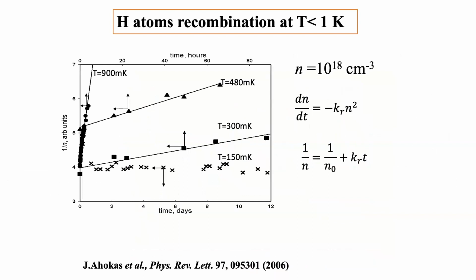We performed this experiment for the first time in 2006, measuring the rate of recombination of atoms at temperature below 1 Kelvin. We made this graph of 1 over concentration versus time, and you can see the slope of this curve became smaller and smaller as we reduced temperature, and even at 150 millikelvin we didn't see any recombination.